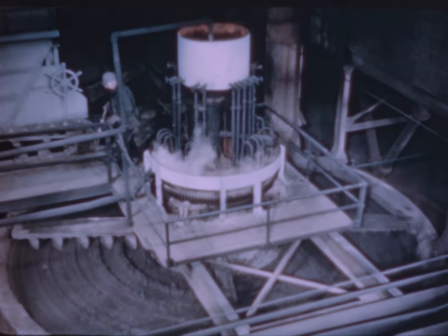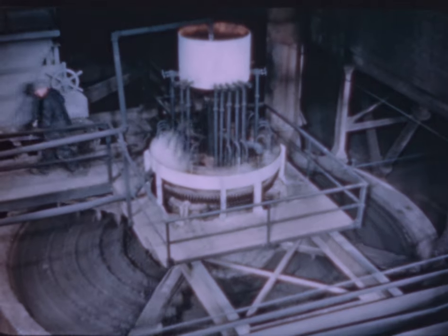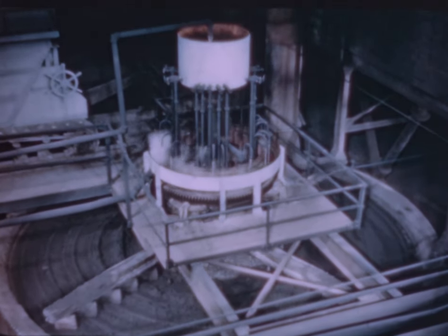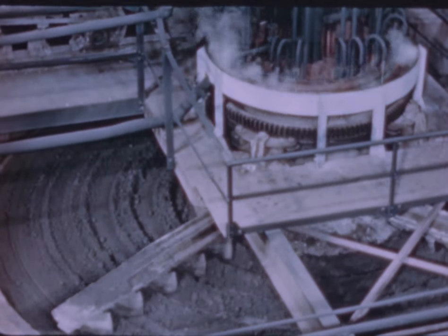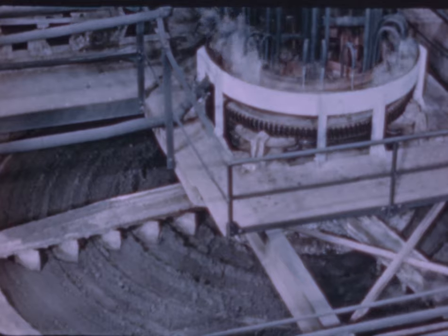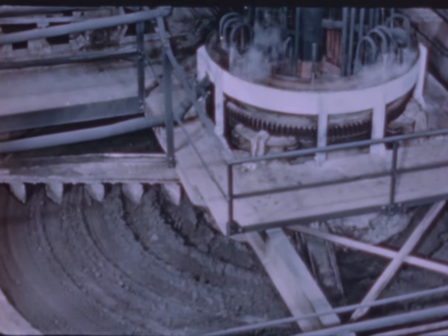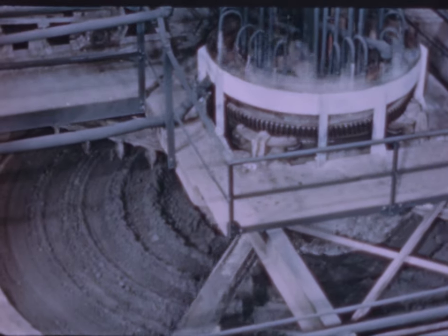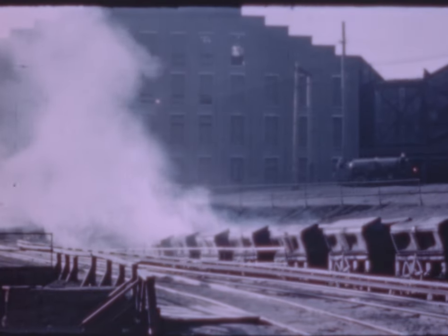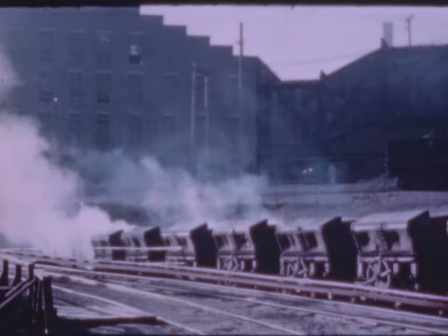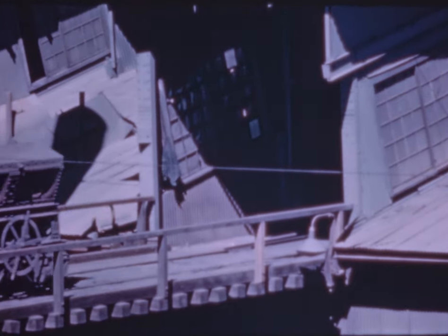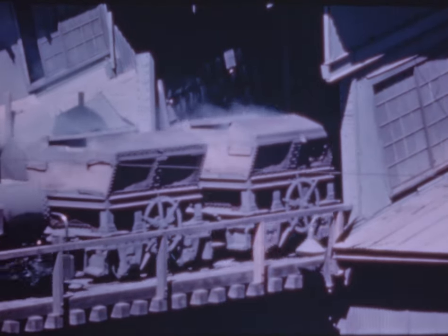In the multiple hearth roasting furnaces, a large part of the sulfur content will be oxidized. Concentrate is dropped on the top hearth, and as it descends from floor to floor, it first becomes dry, then as the heat increases, the sulfur begins to burn, and the roasting operation becomes self-sustaining. Temperatures reach 1400 degrees Fahrenheit, so the rabble arms which spread and mix the concentrate must be water-cooled. The product of the roaster is called calcine. It drops into hoppers at the bottom of the furnace and, still hot, is loaded into tram cars for transfer to the reverberatory furnace building.